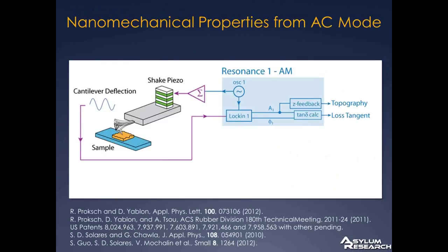AM-FM and loss tangent imaging relies on measuring properties of not one but two of the resonant modes from a cantilever. I'm going to show you how that works right now. Just as for normal tapping or AC mode, we take an oscillating voltage and drive a shake piezo that shakes the cantilever up and down, usually at its first resonance. We measure that deflection with this little blue curve here. That goes back to the controller and is analyzed in a lock-in, and in that lock-in, you calculate the amplitude and the phase.